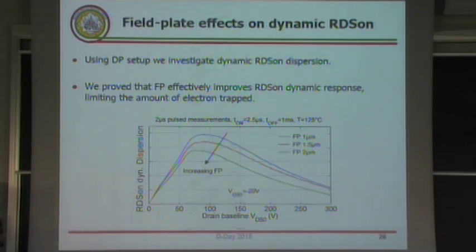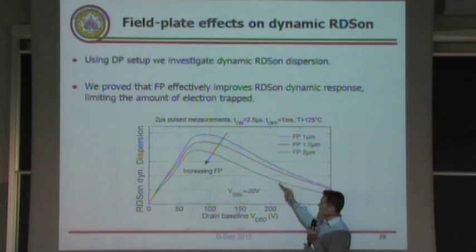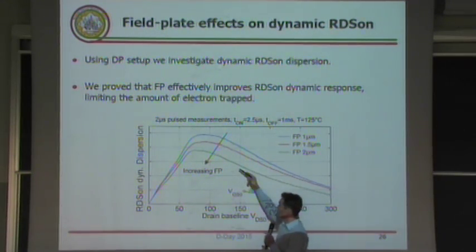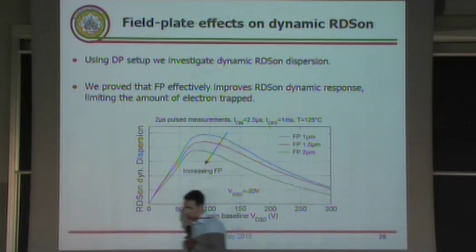However, first of all, we did a complete characterization of this effect using double pulse, and then we demonstrated that the geometry of the field plate, in particular the length, has a strong effect in limiting RDS-on dispersion. So using a long field plate structure, we can really limit the RDS-on dispersion in these devices.